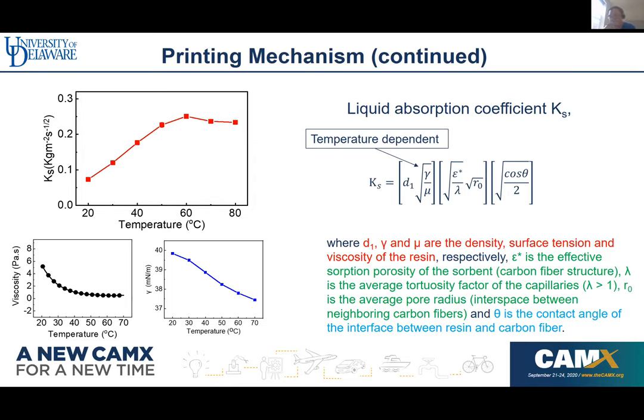Here, just to give an example, we bought a BPA thermoset resin from the market, and we measured its viscosity versus temperature, as well as the surface tension versus temperature. We put everything into this equation, and then we get the Ks value, the liquid absorption coefficient. You can see at the lower temperature the Ks value is low, but once the temperature goes to 60 or 80, it increases. The increase of the Ks value indicates that more capability from our resin and carbon fiber system can contribute to the absorption capability. So the higher number means the resin is absorbed faster into our carbon fiber system.